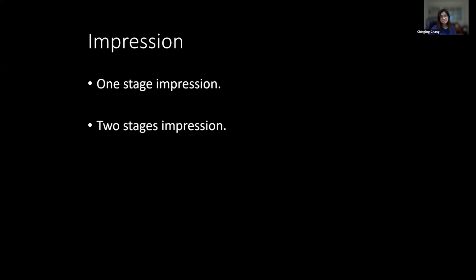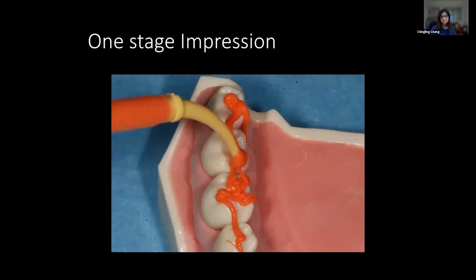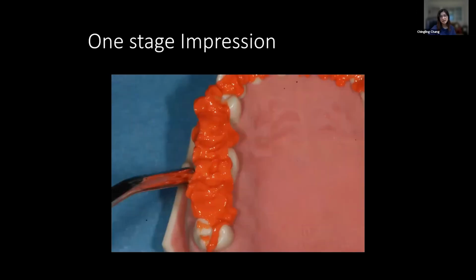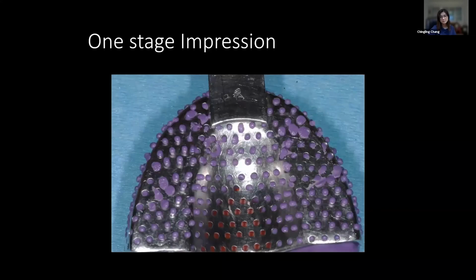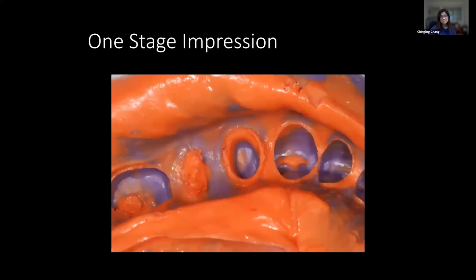As for impression technique, basically there are two different kinds of techniques. One is we just do one stage, or we can do a two-stage impression. For the one-stage impression, we apply the light body on the tooth we prepared, and because it has very low viscosity, it flows nicely. After we apply the material, I like to use air gently, just to blow the material into all the teeth detail, and then use a putty to take the impression. And this is the result after I use the one-stage impression technique. You can see the light body fuses to the putty nicely and catches all the detail of the teeth.